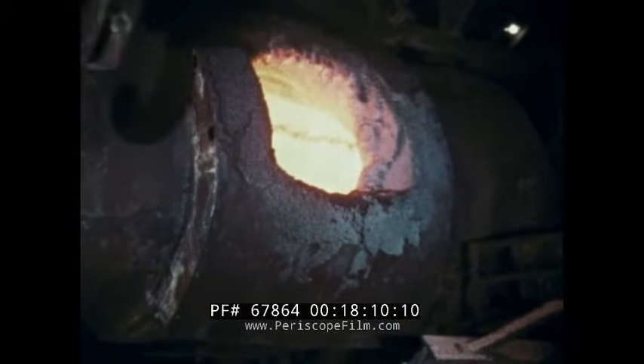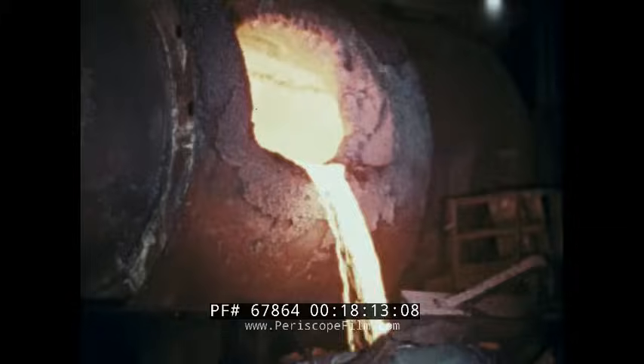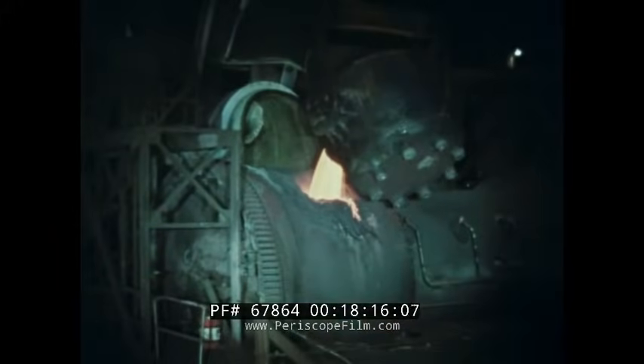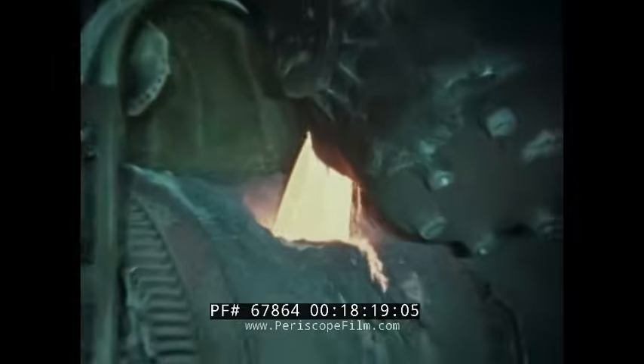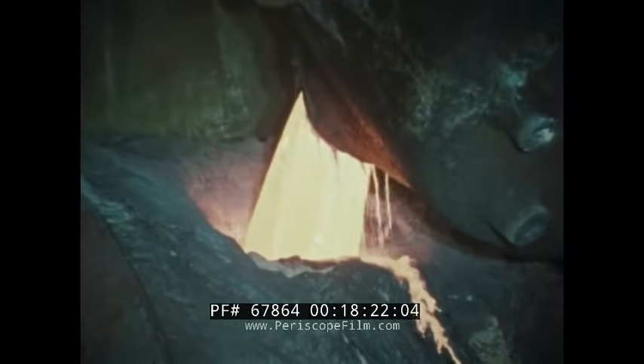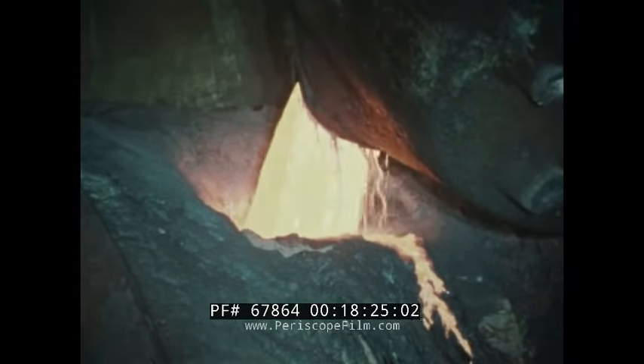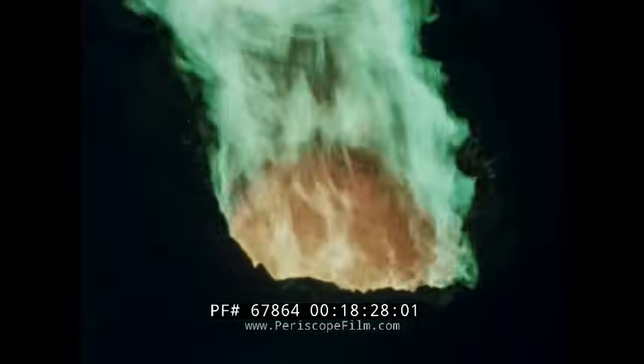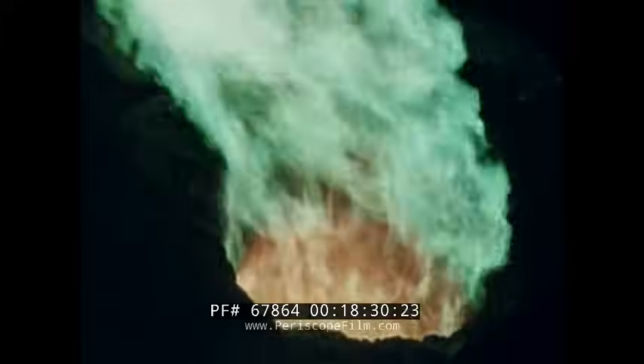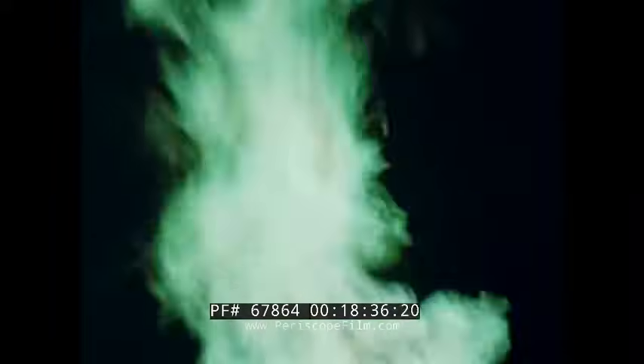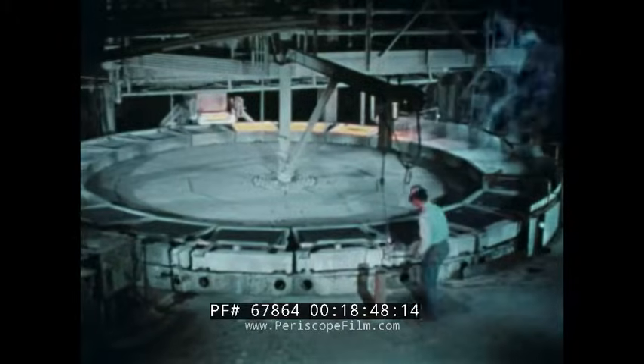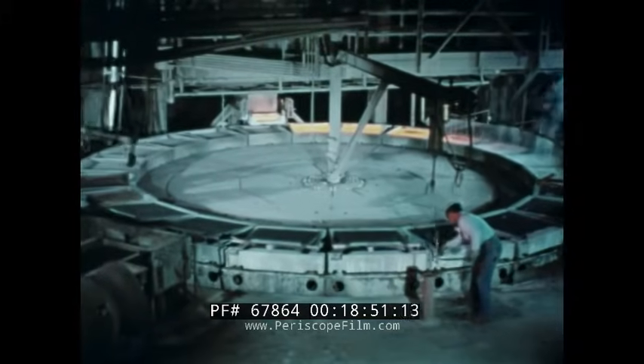The copper from the converter still contains oxygen. This is removed by further treatment in the anode furnace. Here, the oxygen reacting with reformed natural gas goes off as carbon dioxide and steam. Now about 99 6/10% pure, the copper is poured into the molds of the casting wheel to make the anode forms used in refining.